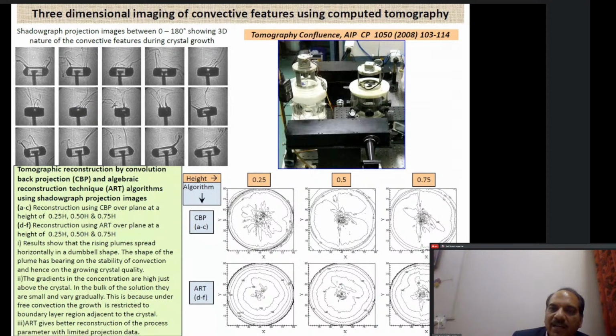This growth chamber had 8 windows, right? The earlier growth chamber which I showed had only 2 windows. This is the 8-window chamber, right? So we were able to record the growing crystal convection fields from multiple directions, and these are the images which we recorded from multiple directions.